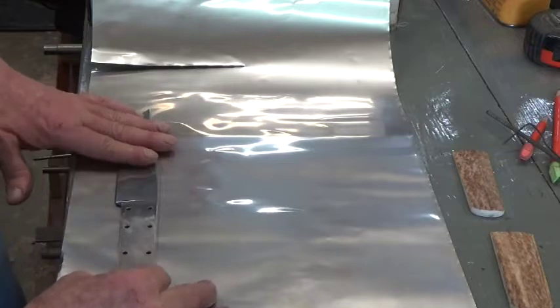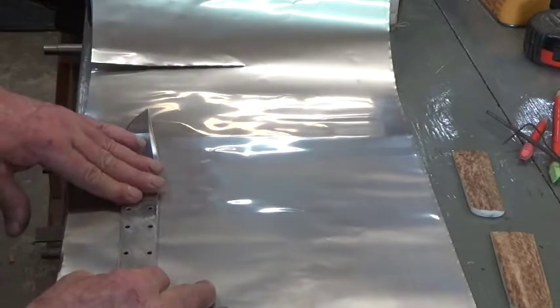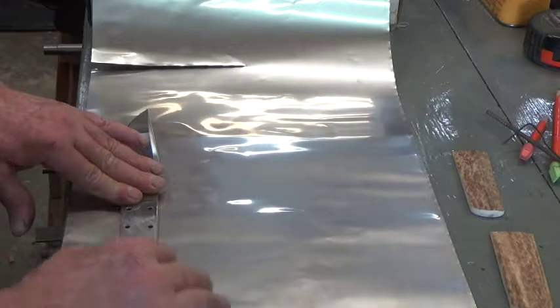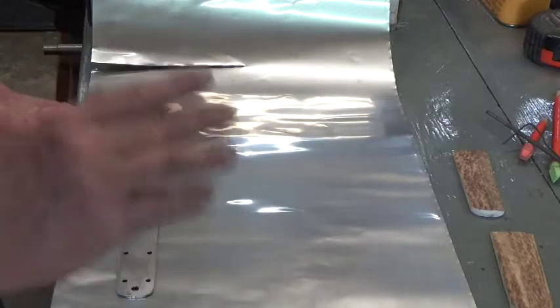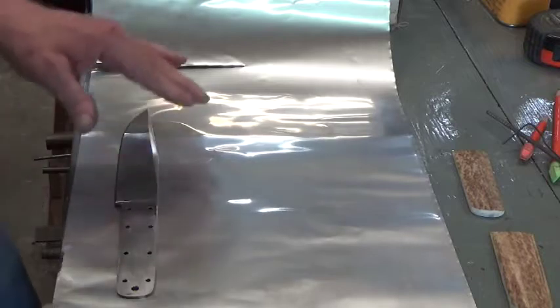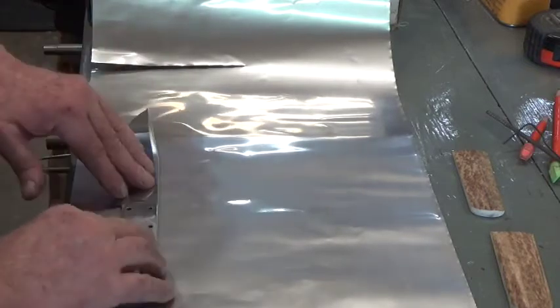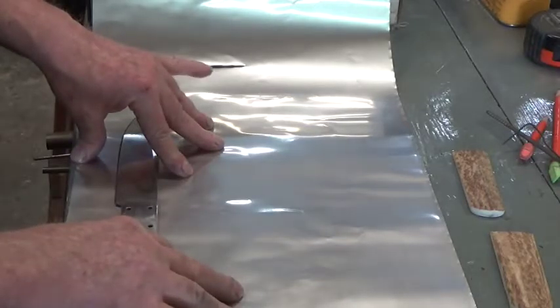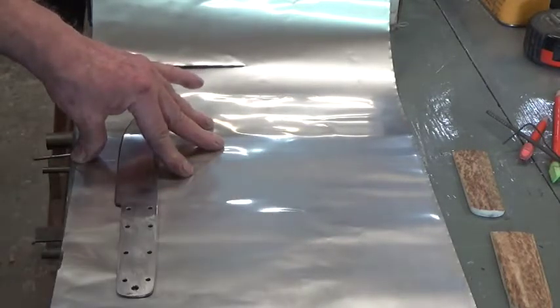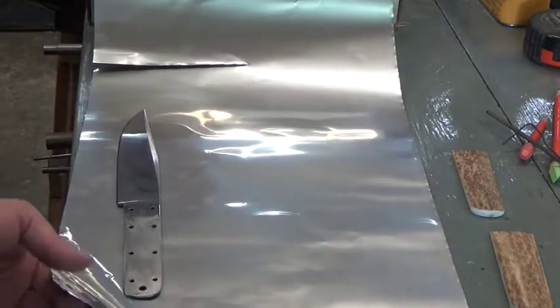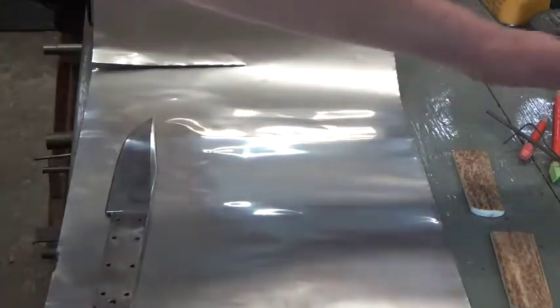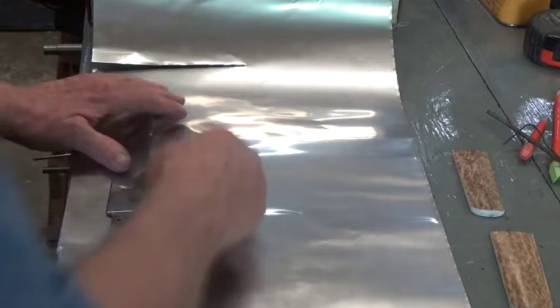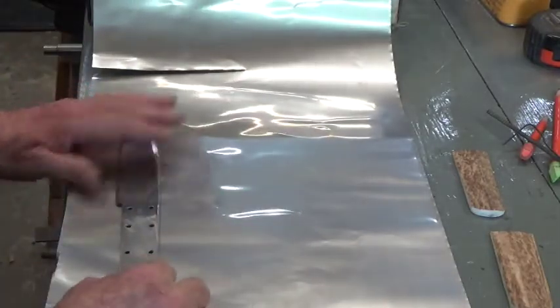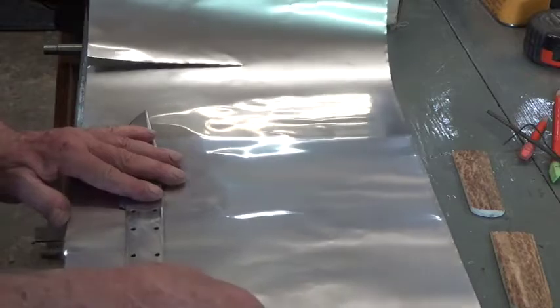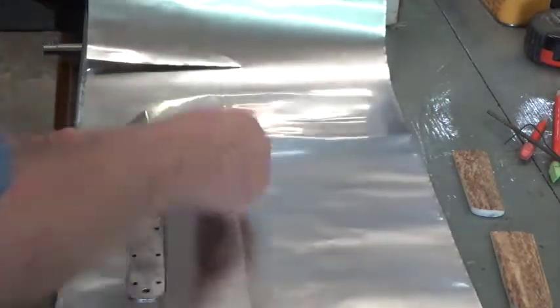And then there is a type 309 heat treating foil that I use for the stainless grades that can go in excess of 1900 degrees. And you have to make sure you use the proper foil. Now I can use the more expensive 309 to do this, but this is only getting up to 1450 degrees, so this stuff is cheaper and will do just fine. Just don't get the two mixed up. And I bought them in different widths just to make sure that I didn't. So I want a piece about, it's a big knife as they go, so I want a piece about that big.